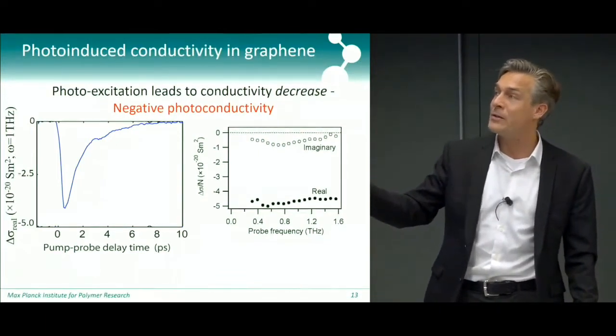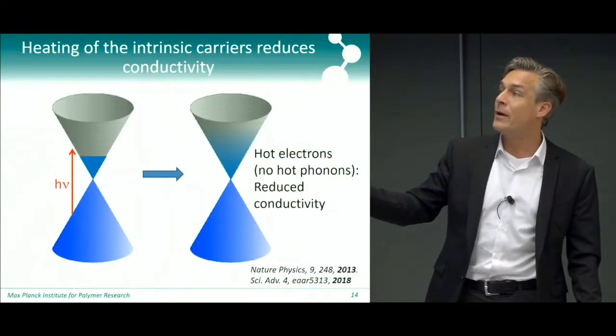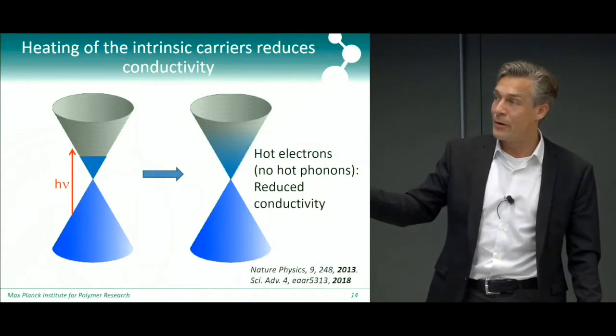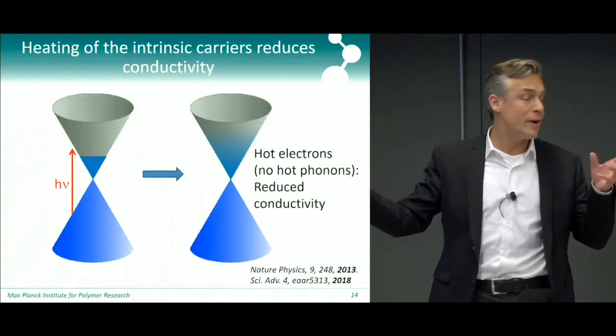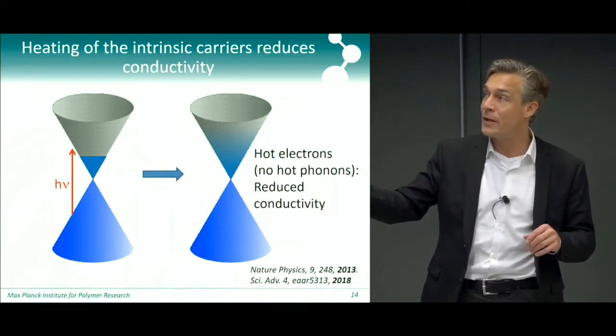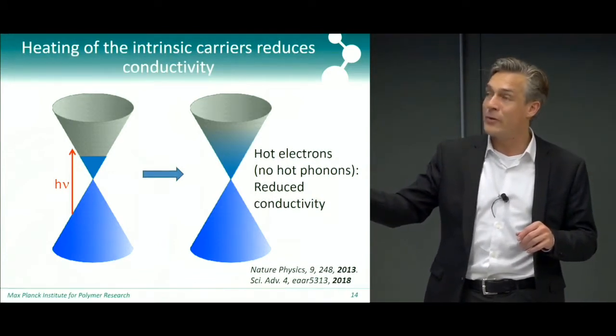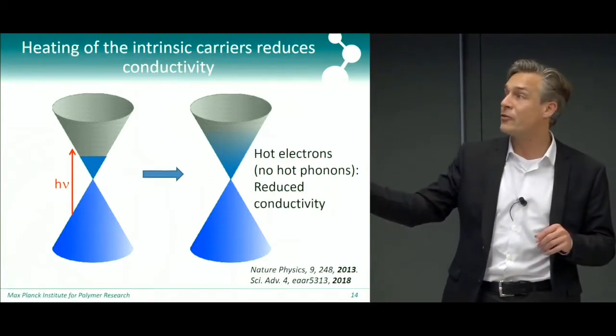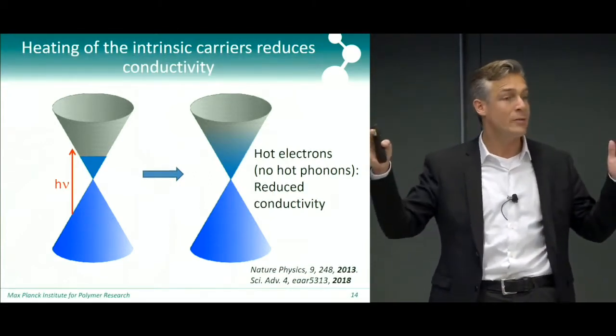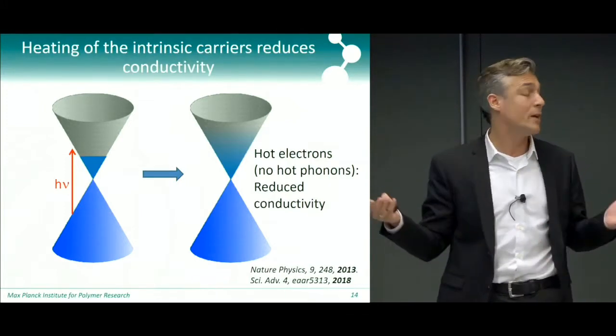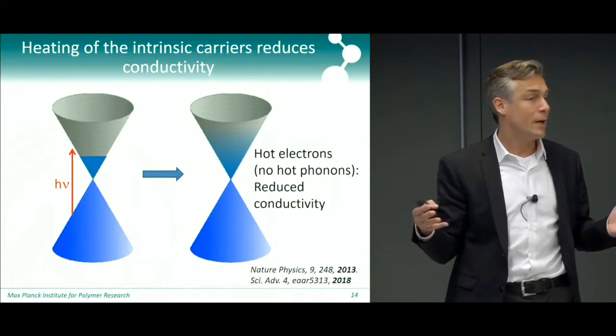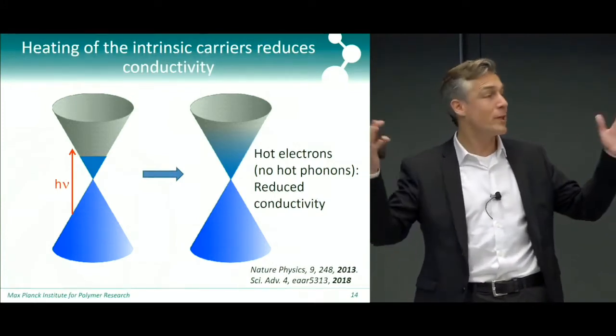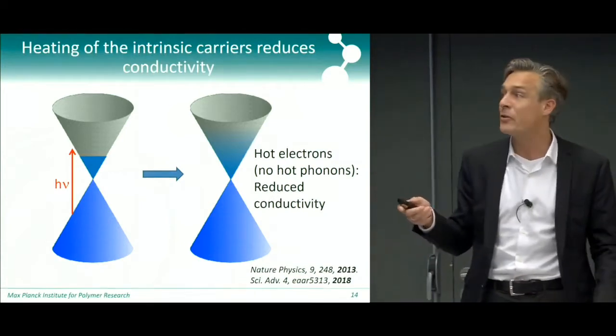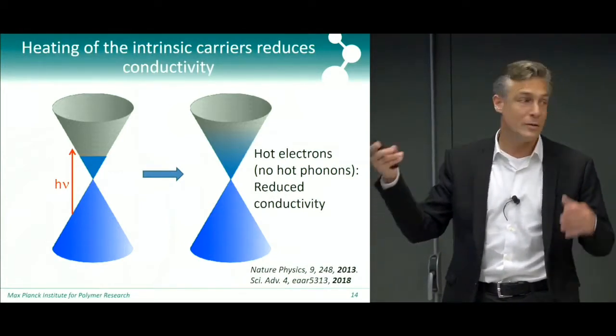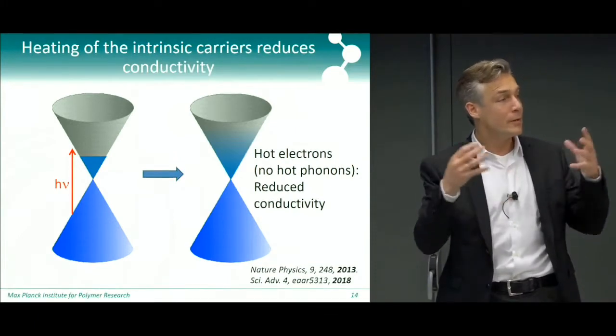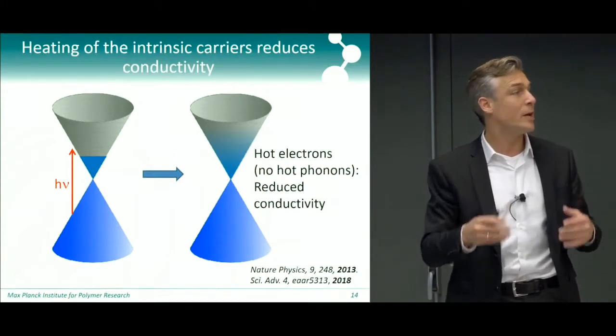Really what is happening here, this negative photoconductivity is very simple: you photoexcite electrons, they scatter very quickly amongst themselves and amongst the electrons that are there because of the doping, and within about 10 femtoseconds you get a hot electron distribution. So you get a Fermi-Dirac distribution that is now hot, and those hot electrons simply have a reduced conductivity. And so there's no magical gain, there's nothing special about this. It's just the optical pulse heats up the electrons that are there due to the doping, and they have a reduced conductivity.